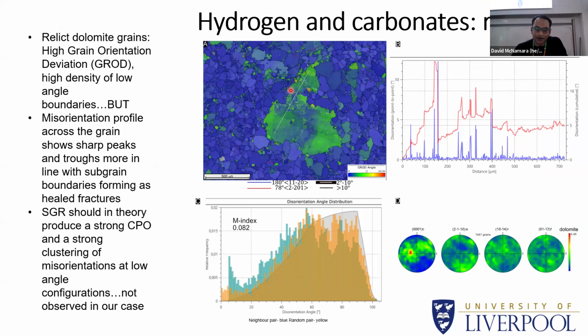But the thing is, once we drew a misorientation profile across the grain, and this is the profile along this white line, we see that there are a number of peaks, yes, but after every misorientation peak corresponding to a low angle boundary, there's a trough, so it drops off. If it were to form by subgrain rotation, then we would expect the misorientation to have a gradual gradient increasing from core to rim, but that is not what we see. Instead, we see these constant pronounced peaks and troughs. So this led us to conclude that these were more likely low angle boundaries that represent healed fractures rather than proper subgrain rotation.